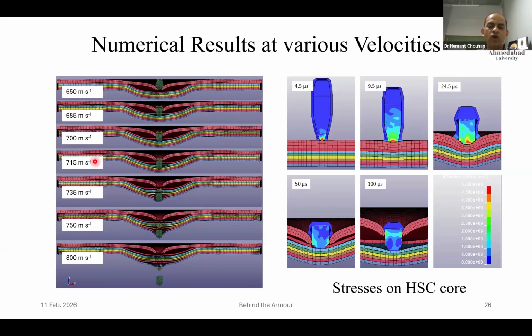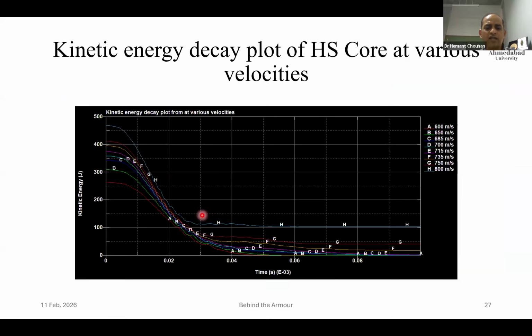And in the Indian context, we always have plus minus 15. So 715 is the highest speed. At 735, we have designed that the tip will get exposed. The bullet is not penetrating as such, but it might be visible at the back. Less than this, at any value, your bullet is well within the composite. At 750, it is penetrating, and at 800, for the same set of parameters, it will actually perforate completely. So these are the instances at the various time units, and the kinetic energy available with the projectile after the completion of this much time.